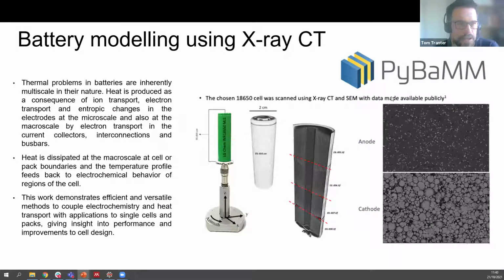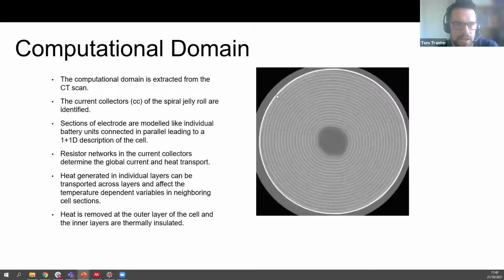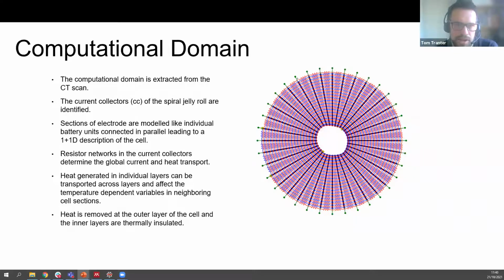Now this is what I've been doing over the last couple of years. I've been taking these tomography images and making models out of them, using the CT image directly. I can essentially use this resistor network approach, where I'm dividing up the cell into different regions, and I'm applying a P2D model at each one of these little interconnections, but resolving the global current and the heat transport at the cell level. So this is going to be useful to integrate with the acoustic models that we'll be developing. As we can capture those different changes in states and changes in temperatures with this model, we can then start to predict what the acoustic response is going to be throughout the different spatial regions of the cell.